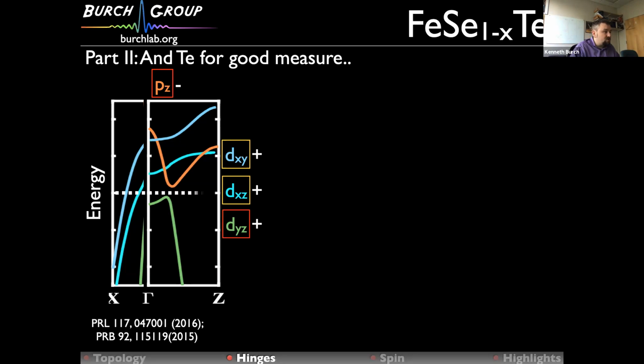What's amazing, though, is, of course, your Fermi level, even if it falls in this gap, would still cross the dxy and dyz bands in the plane at kz equals 0. And of course, you have your Fermi surfaces at M. And what that means is you could have a material where in the bulk, it's superconducting, and you would also have these surface states, and therefore you could get basically a kind of perfect proximity effect where you don't need to combine materials, you just get it for free.